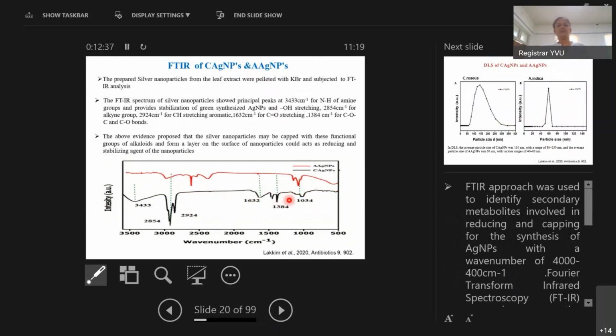After that, I investigated the FTIR analysis of the green synthesized silver nanoparticles. These silver nanoparticles show the presence of different phytochemicals from the leaf extracts, analyzed through Fourier transform infrared analysis. The prepared silver nanoparticles from the leaf extract were pelleted with potassium bromide and subjected to FTIR analysis.